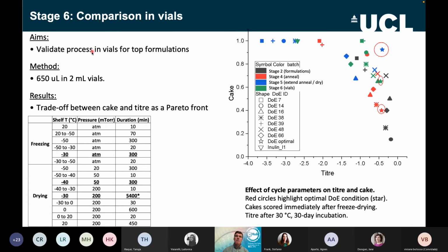Okay, so that's all done in microplates so far. One thing we needed to establish was whether, now shifting into vials, we're going to change everything. We had done that work at the beginning to show that the vial performance and the plate performance was similar, but you just never know. So what we did was we took our best process up to this point and a range of formulations into vials, and we used a 650 microliter fill in 2 ml vials, so standard freeze-drying vials.